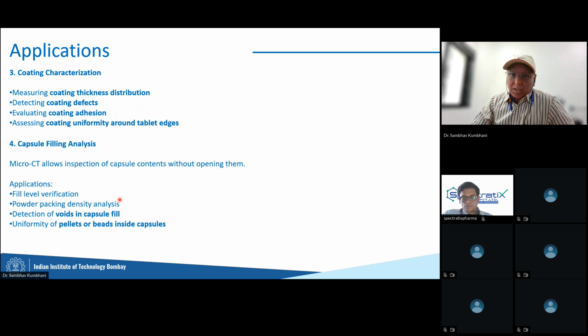Coating. A lot of times the tablets are coated, and the coatings are released very slowly in your body, right? So the coating thickness, coating quality, whether there is deformation in the coating, and whether the coating is uniform or not, all that can be seen using CT. I already mentioned capsule filling. How much is the content, how much is filled, is it packed thoroughly, or are there a lot of pores? When you pack something, there will be gaps in between the powder. You want to compactly pack it or you want to loosely pack it, all that can be checked using CT.